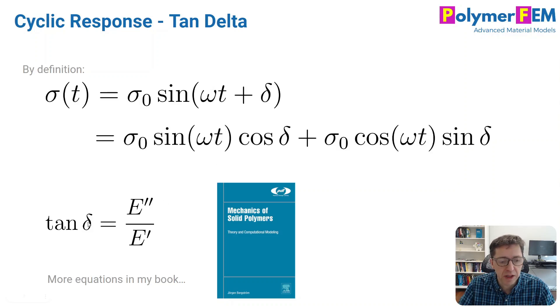And then you can figure out very quickly that tan delta, this delta phase angle, is given by this loss modulus divided by the storage modulus.